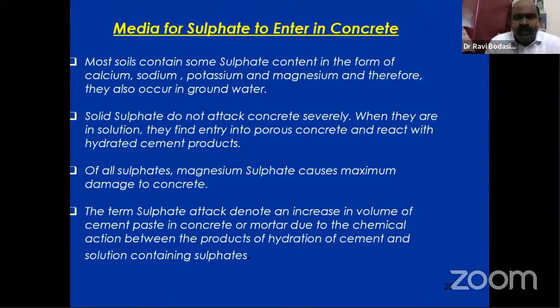So this solid form will not have that much effect on the structures. But when these contents are mixed in water, and if water is percolated through our structures with porous and weak junctions, then definitely the sulfate attack will cause a big problem to the structure, and it will increase the volume of the cement paste.